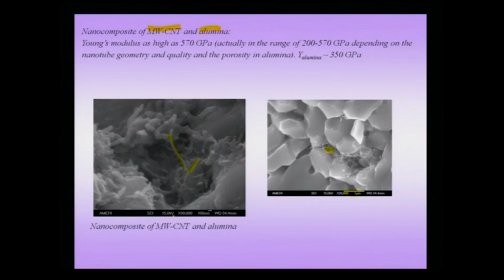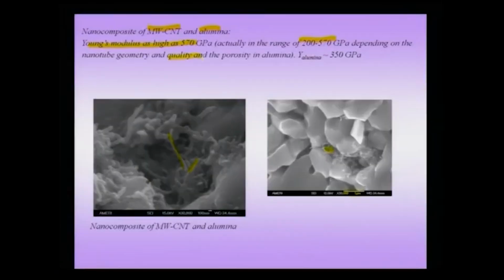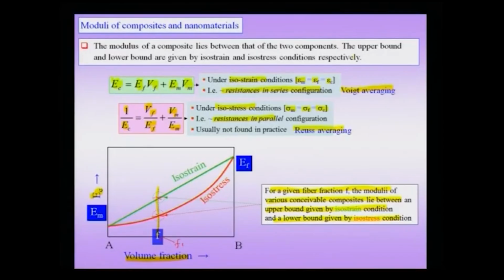So, these multi-walled carbon nanotubes have been used to reinforce alumina. The Young's modulus of such a composite has been found to be as high as about 570 GPa, and the range typically has been found between 200 and 570 GPa. This of course depends on the nanotube geometry, its length, the number of layers in the multi-walled nanotube, the quality of the nanotube, and the porosity in the alumina. But if you note that the Young's modulus of alumina is smaller, then you can get a considerable benefit in the modulus by adding a nanotube reinforcement to the ceramic. This has additionally been found to give a fracture toughness increment, which we do not deal with here, but it is important to note that when you add nanotubes to alumina, there are other benefits you get. So, this example of a carbon nanotube is an example of making a composite and therefore enhancing the modulus of the material.